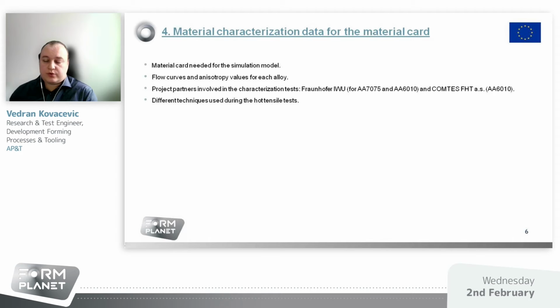Apart from the tool scans and the press kinematic parameters that we gained from the forming trials, the FEM model would be incomplete without the proper material cards for the alloys. From previous work, AP&T already had access to heat transfer coefficients depending on gap and pressure for the alloys, but lacked flow curves and anisotropy values. Therefore, together with our project partners Fraunhofer and Comtess, we defined a characterization matrix for hot tensile tests that were performed.